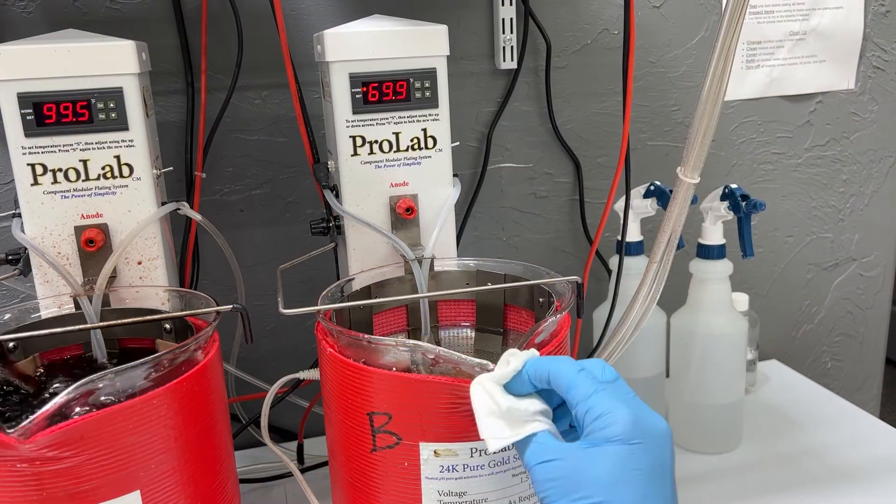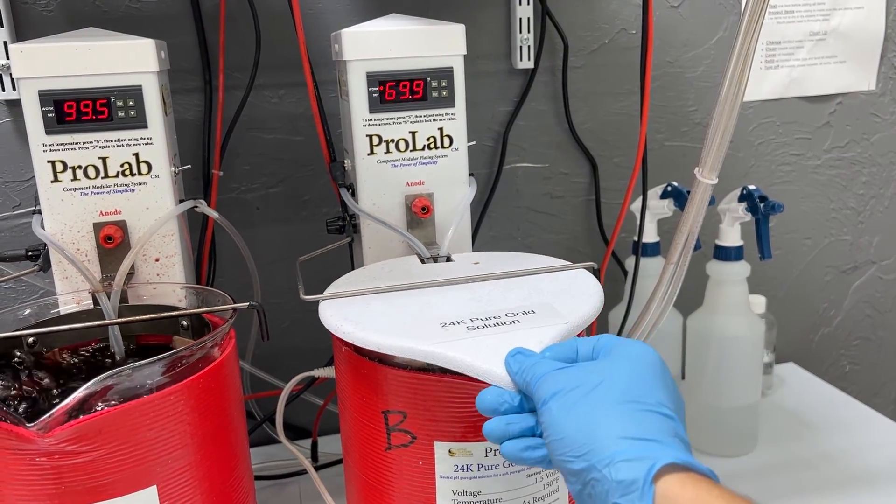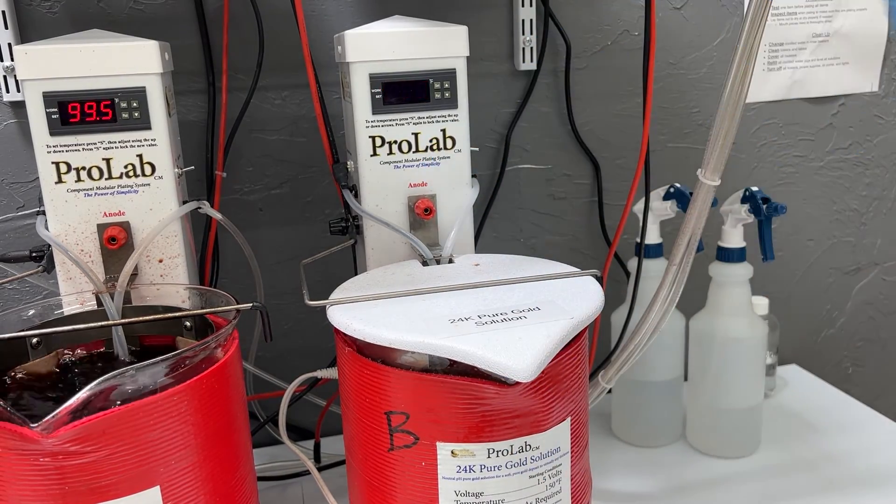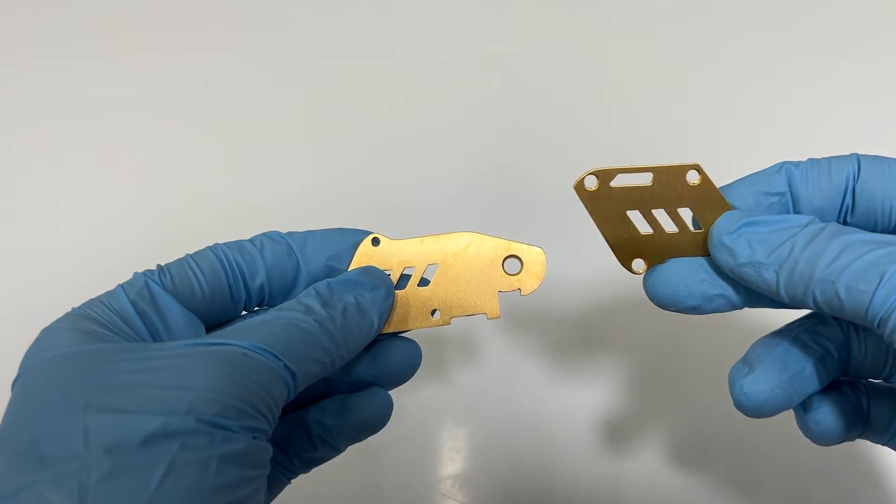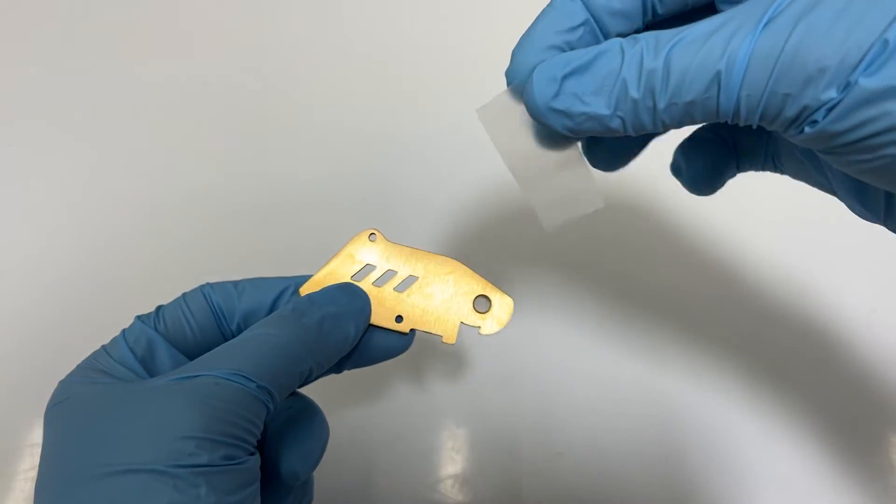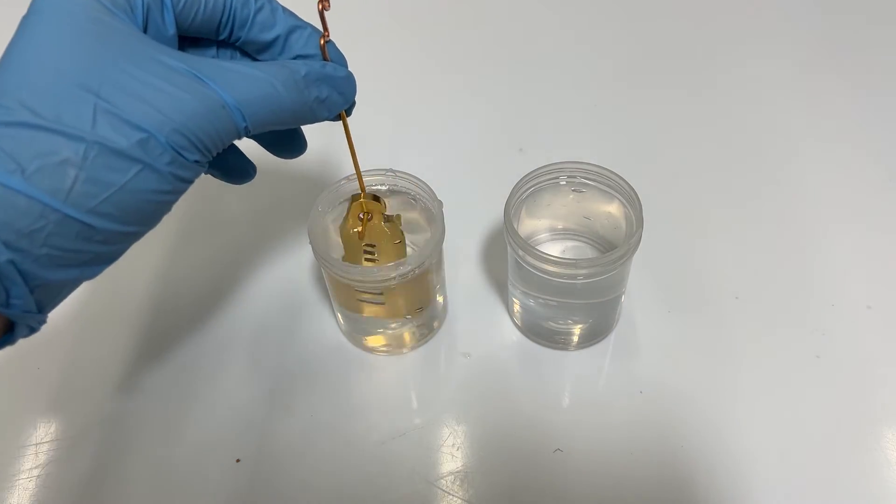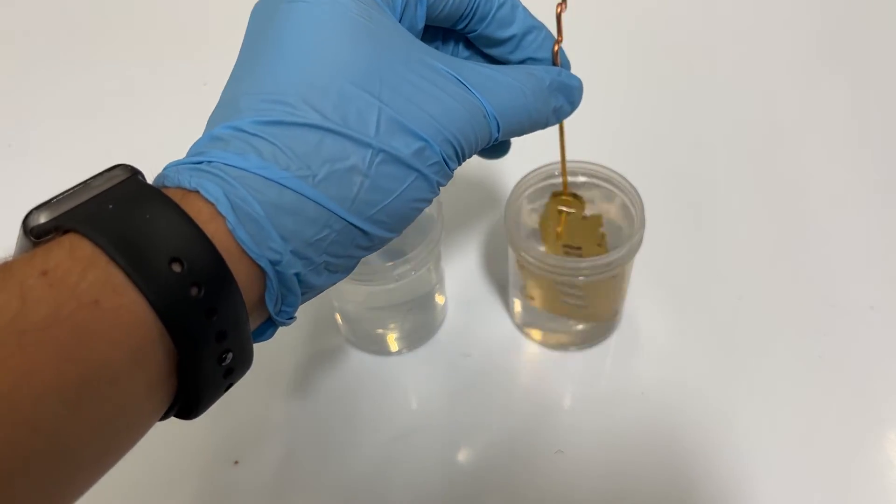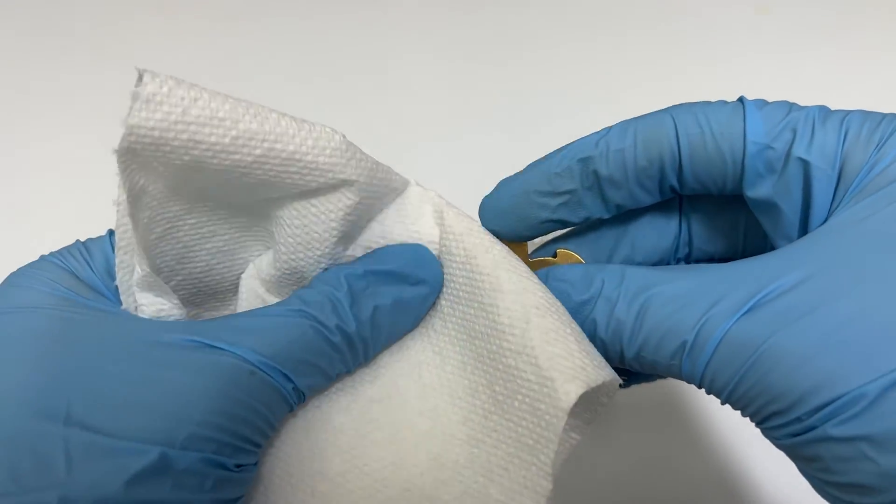After. When you are finished plating there are several things that you can do to wrap up your plating job to maintain your solutions and equipment. Do a final inspection of your plated items. Make sure there are no flaws and do a tape test to check for proper adhesion. To remove the surface of water spots dip your items in distilled water then methanol and dry with a heat gun. Don't package up any items until you are sure they are fully dry.